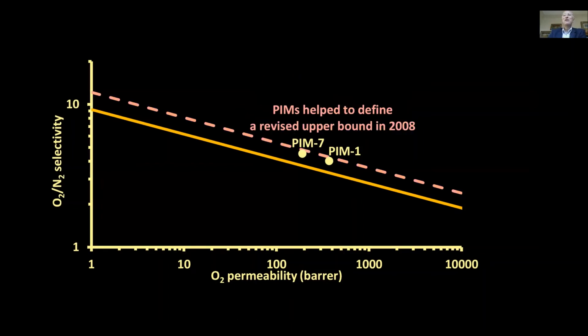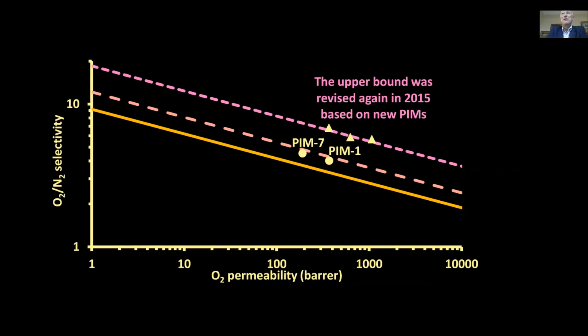Well, time moves on, because in 2008, Lloyd Robeson said, well, the upper bound has moved now. So he took our data and data from a few other polymers and drew a new line. So now we researchers had to try to do even better and find new materials that did even better in terms of how they perform. And in fact, ourselves and colleagues in other places in England and elsewhere across the world have created new polymers, mostly PIMs, which have pushed that upper bound even further. And so we can see how research has improved what is possible. And because these plots are on a logarithmic scale, that's a big change that we're seeing over that time.